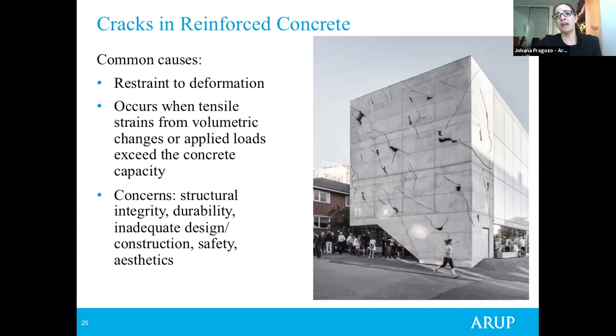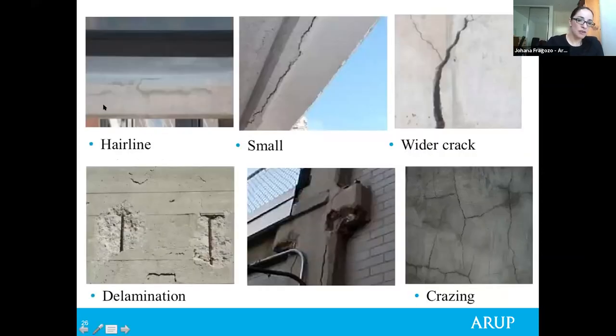Subject to the corrosion expansion of the reinforcement, the concrete will crack or spall. This next slide shows different types of cracking concrete. It starts as hairline, and then the widening of the crack allows water penetration. The crack keeps widening and eventually results in delamination. There could be as well some spalling of concrete surrounding steel elements such as columns or beams due to insufficient cover or inadequate quality of the concrete.